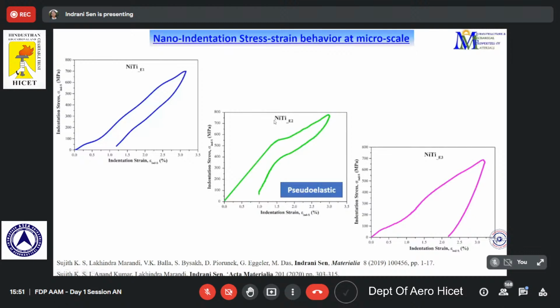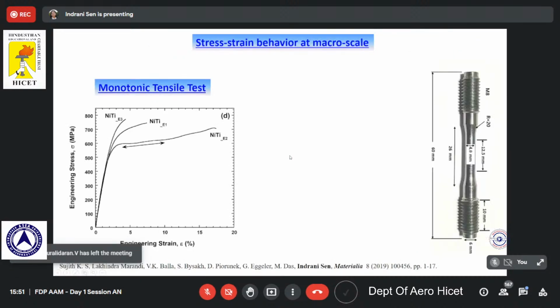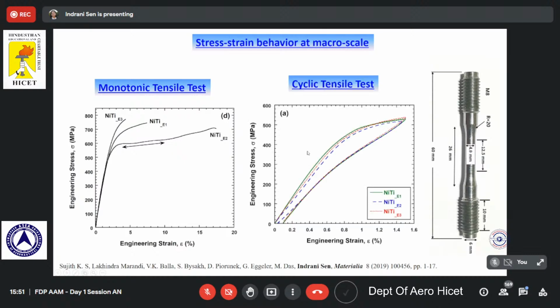And to our savior comes this alloy prepared with optimum laser energy density in the middle, which shows a perfect pseudoelastic plateau and so on. Okay, now to find this out completely, we did the macroscopic tensile test, like the regular conventional standard tensile test, and you can see that the one with optimized laser energy density actually gives the highest deformation, and we can figure out the pseudoelastic plateau also very clearly from this structure.